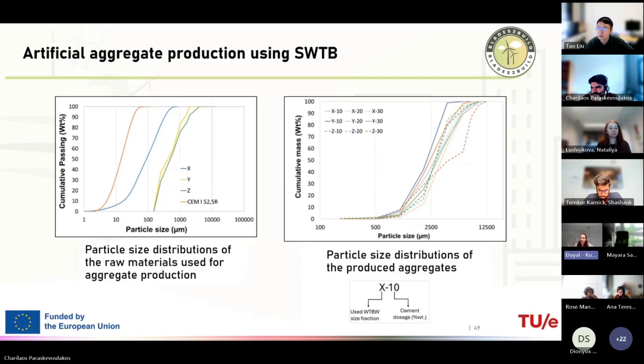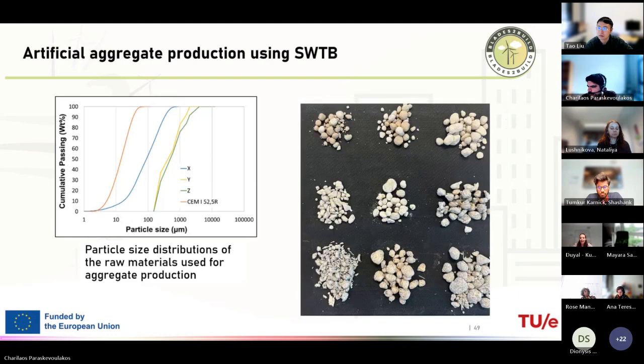And here you can see the whole aggregates almost reach the point to be able to replace the whole curve of the fine and coarse aggregates inside of the concrete. So it is possible to create the whole curve from fine aggregate to coarse aggregate. And these are some figures of the different artificial aggregates that we have achieved after the pelletization process.